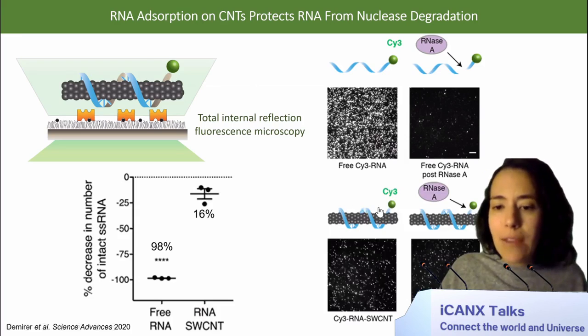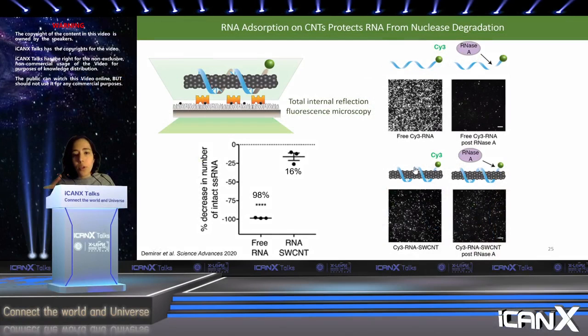However, if we take this fluorescently labeled RNA and first load it onto a carbon nanotube and then immobilize that construct and treat it with RNase A, we do see some degradation or some elimination of fluorescent spots, but nowhere near as much degradation of the RNA as we did in its free counterpart. These results suggest that in addition to helping shuttle these cargoes inside plant cells, another mechanism by which these nanoparticles could be helping gene expression or RNA-based siRNA silencing is in the protection of those cargoes until they are able to be functional inside the plant cell.